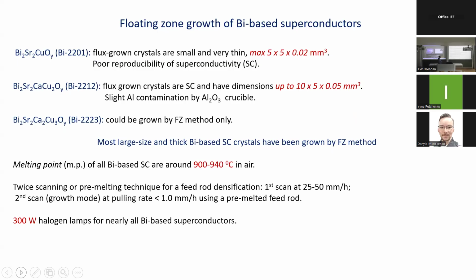Again, the melting point of nearly all these materials is around 920, 930 degrees in air. So feed rods are very porous, but nevertheless, people have developed the so-called twice scanning or pre-melting technique for feed rod densification. Once you get a zone between feed and seed, you pass the zone at very high speed, and you densify the feed rod in this way. So this pre-melted rod, then you use for the growth.